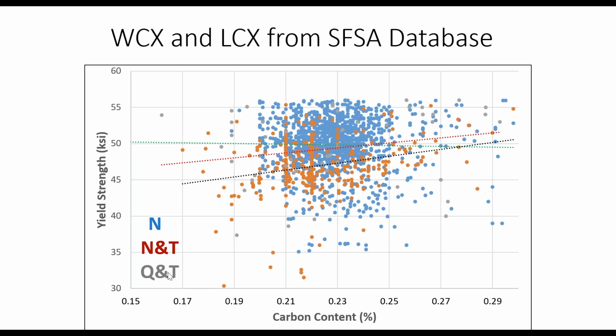So one of the things we want to do in our industry is make a series of carbon steels that are transparent to our customer base. So using this database, you can see that our customers really look for three flavors of carbon steel. One is 36 KSI, which is the old historic lower limit, and you can see we virtually always meet that. The common next generation of steel products that we don't have a standard for says that carbon steel ought to give you 42 KSI, and you can see that that's not a real challenge. And then the next generation says 50 KSI, and you can see about half the points are still higher than 50 KSI.